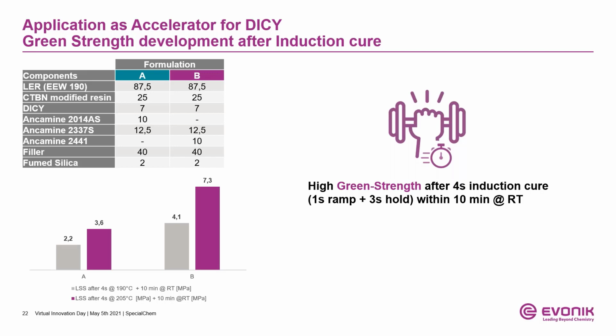For testing, the bond line of all lap shear samples was heated up to 190 centigrade or 205 centigrade respectively via induction and kept at the respective target temperature for 3 seconds. The lap shear strength shown here was evaluated after 10 minutes storage of the specimen at room temperature. The achieved lap shear strength values again indicate great green strength capabilities with a distinct performance advantage on side of the combination Dicyandiamide with the Ancamine 2441 and the 2337S at this point.